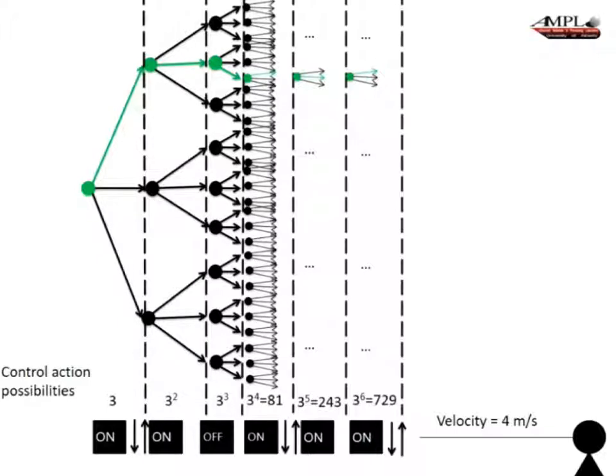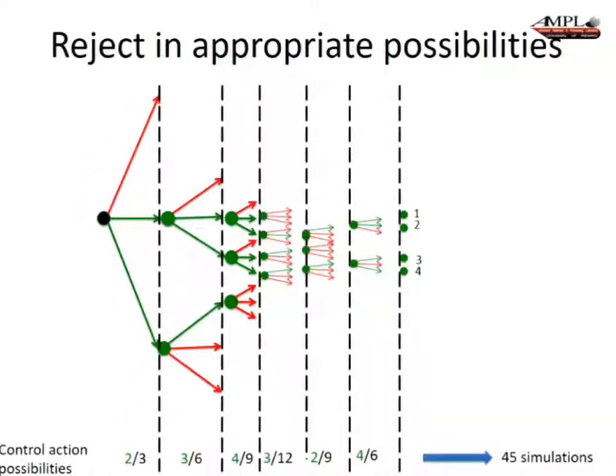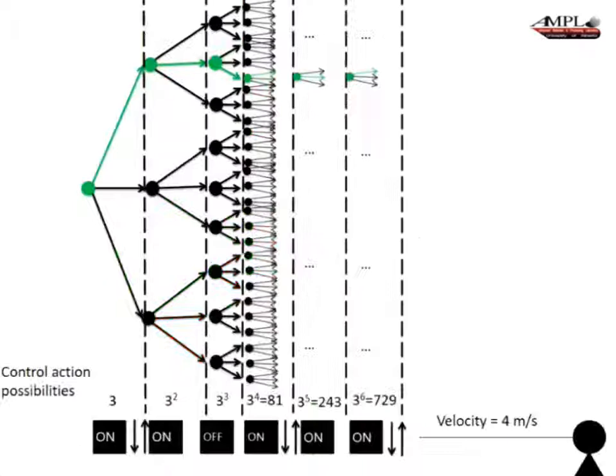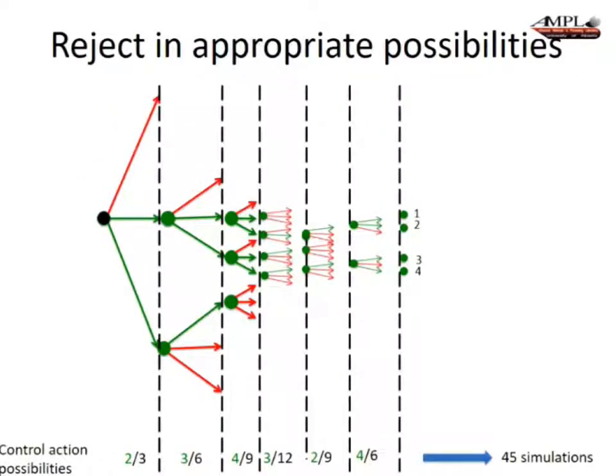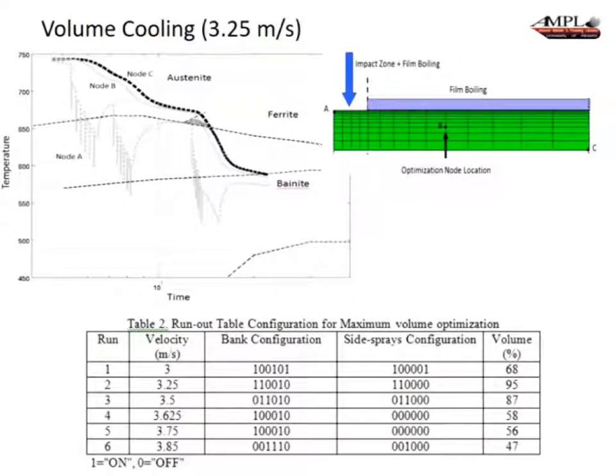And by doing that, you can reduce the number of iterations you're doing for calculations quite significantly. So this shows you, for example, the reduction of the number of steps with a branch and bound. I'll just go back 1 minute. So with 6 banks, that would have led you to 729 simulations, if you do them all rigorously, every single one. But if you do the branch and bound technique and just pick the best ones every time you step through, you can reduce that to a much smaller number of 45 simulations. So that's a major improvement in terms of execution time.